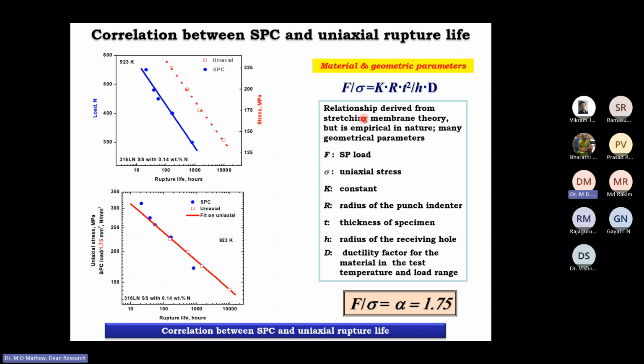So once you use this conversion relationship and convert the data, you will get an excellent correlation between the SPC test and the uniaxial creep test in terms of the rupture life of the material. Again, this F by sigma turns out to be about 1.75 for most materials.